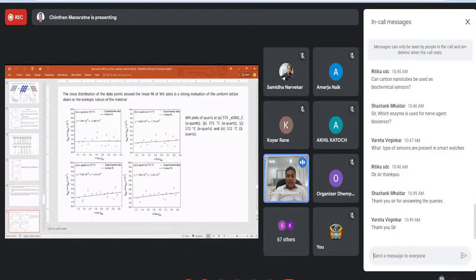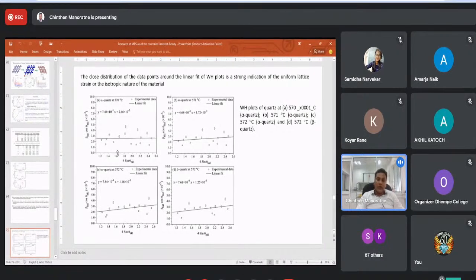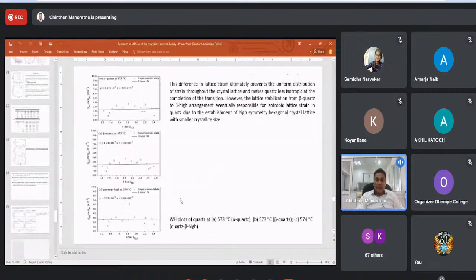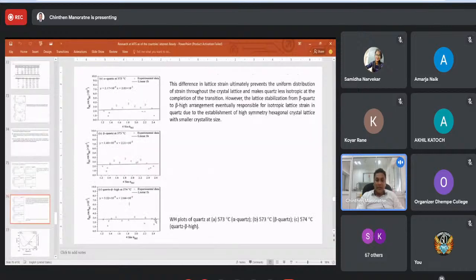So these are some findings. Here we have also employed the Williamson-Hall method to calculate the microstrain. At 573, the scatter is not widely scattered, it is narrowly scattered. That means we have produced a uniform, stable structure.